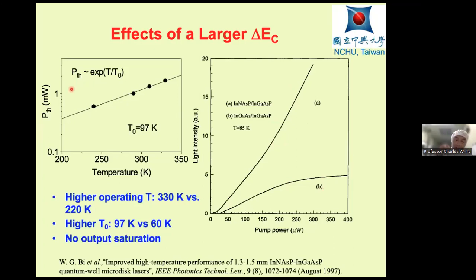And this shows the threshold power. This incident excitation power is vertical, it's optical pumping. And threshold power goes like exponential T over T0. So the larger the T0, the smaller the effect of the temperature. And so here, with dilute nitride, we have a higher T0. So all these mean that we have a larger conduction band offset. Okay.